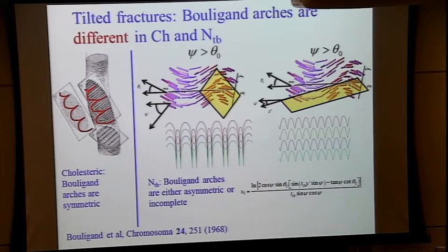But that kind of doesn't give you a satisfaction of being absolutely sure that what you are seeing is exactly the twist-bend nematic. So you need some additional experiments to do, because, for example, this periodic layering might be simply a smectic, in which you have the 1-dimensional periodic order, and the replica just picks it up. So you do X-ray, and the X-ray tells you, no, there is no density variation. It's just all homogeneous. So then you work more with the specimens, and you are trying to reach a situation when the fracture is not parallel to the heliconical axis, but tilted.